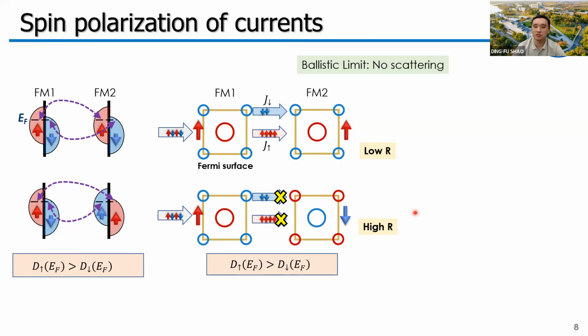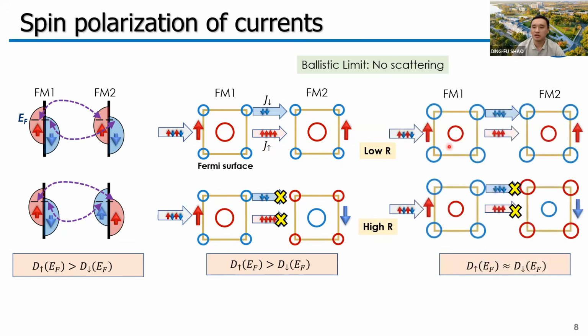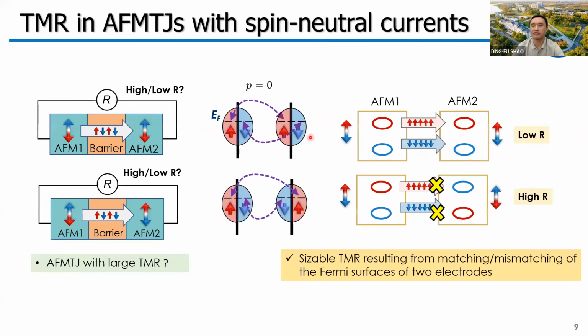Next, we can consider a different situation where the spin up and the spin down Fermi surfaces have a similar value. In this case, we will have a nearly spin neutral current, but we can still have a low resistance state and a high resistance state by matching the Fermi surfaces of the two electrodes. So obviously, if we can find an antiferromagnetic metal with such a non-spin degenerate Fermi surface, we can use this antiferromagnet as an electrode to build the tunnel junction and get the TMR by matching the Fermi surfaces.